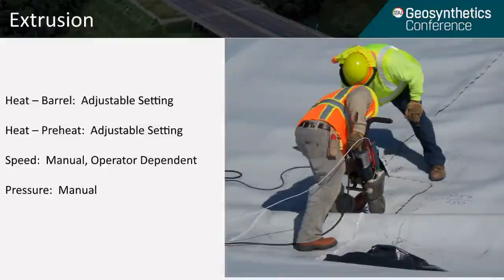Extrusion fillet has two sources of heat. The first one is just a preheat ahead of the nozzle of the gun. The barrel is where the welding rod comes out, and both of those are adjustable settings. In the barrel, you're trying to melt the extrudate rod so that it is the right temperature for blending with the geomembrane. The speed is going to be how fast the operator moves, and the pressure is going to be manual. It's going to be the weight of the gun and whatever pressure the operator is putting on the weld.